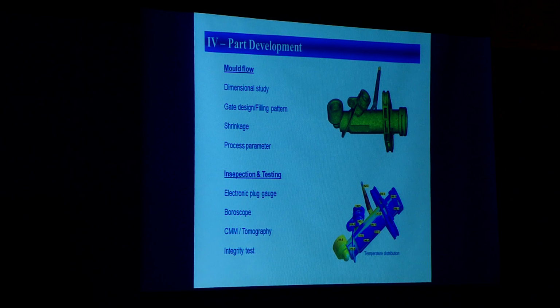Once the part is molded, how do we inspect this part? We had to use special gauges for this, not the conventional ones, the special electronic plug gauge. Then a boroscope had to be used to check whether there were any problems or defects in the bore. Any scratch mark in the bore or any other defect in the bore could very seriously affect the movement of the plunger and can lead to a failure of the part.